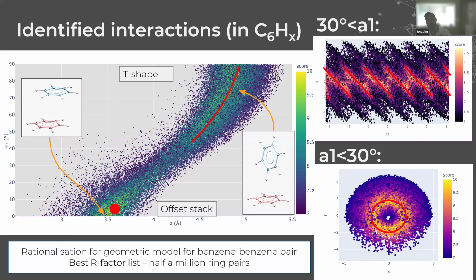And then the graph moves through higher Z values and higher A1 scores until you get this interaction that's defined in the top right, which is T-shaped, where you have centroids slightly further away and the interplane angle being closer to 90. So this is our rationalization for a geometric model for benzene-benzene pair interaction, and all of the data here has come from the best R factor list, which is 500,000 ring pairs.